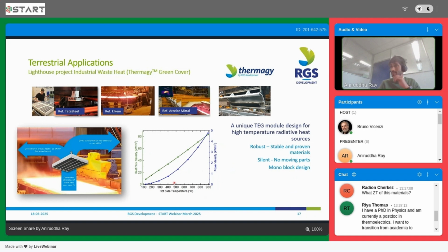In this plot, you can see some of the characteristics of our all silicon germanium based module. It is quite good, especially above 500 degrees centigrade. That's where these silicon germanium materials start performing. And when we notice this gap, we started looking at some more materials which can operate better between bismuth telluride, which is max 150, 200, and up to 400 degrees centigrade. So there clearly was a gap over here.